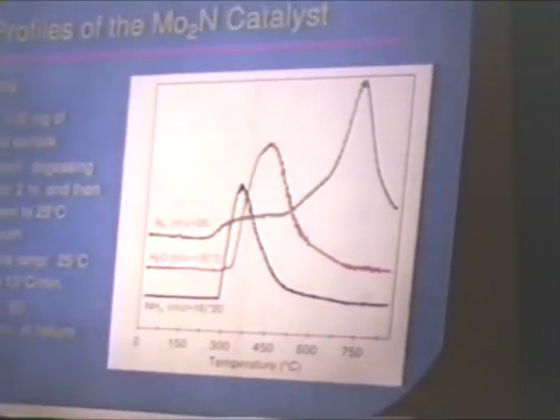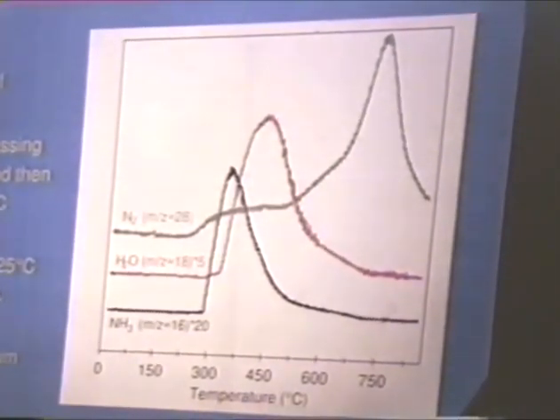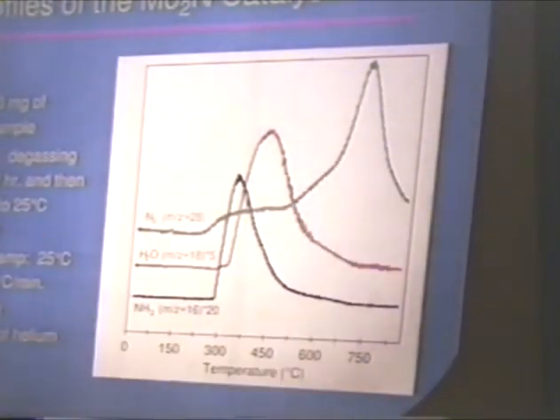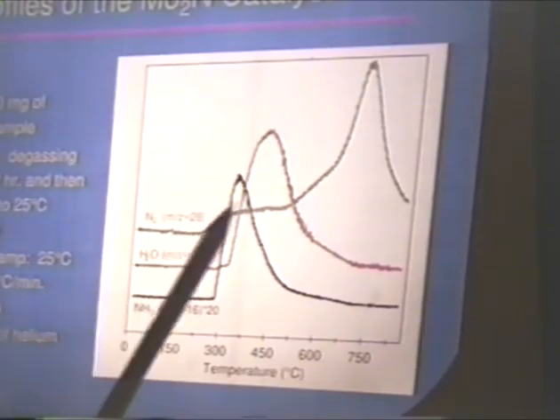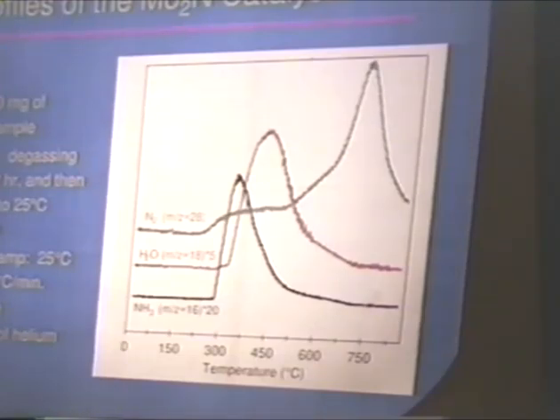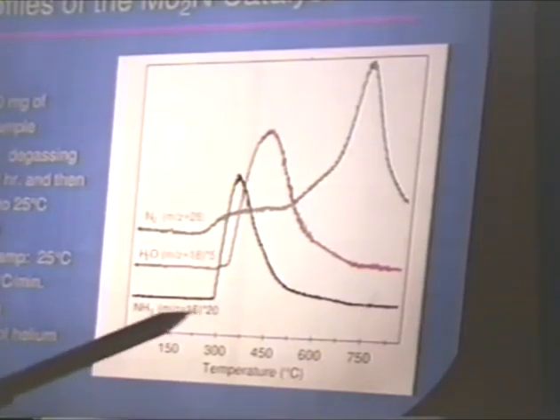If we take an initial look at the TPD profiles of the molybdenum nitride catalyst, what we're seeing here is an early nitrogen desorption feature, which is taking place starting as early as 150-200 degrees centigrade, followed by a much larger nitrogen desorption. We're assuming or suspecting that the early shoulder that we see is the desorption of nitrogen from surface, subsurface. However, once we reach this temperature around 750 degrees centigrade, probably nitrogen is beginning to evolve from the lattice of the nitride structure.